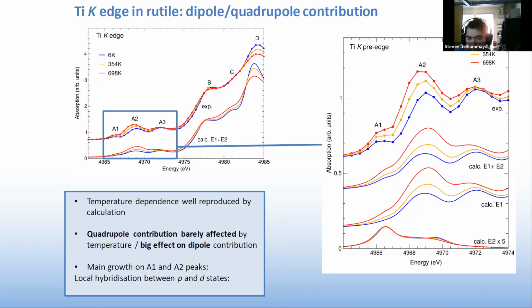Once again, we can see that there is a different intensity regarding the effect of vibration on the dipole and the secondary channel, which is here the quadrupole channel. The effect on the dipole contribution is much bigger than the effect on the quadrupole contribution, with the quadrupole almost not changing whatsoever. Whereas on the dipole, we have a big increase of the A1 and A2 peaks mainly. So once again, we're going to try to explain that.